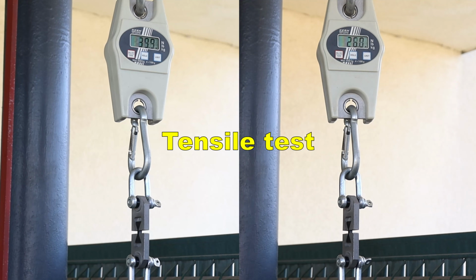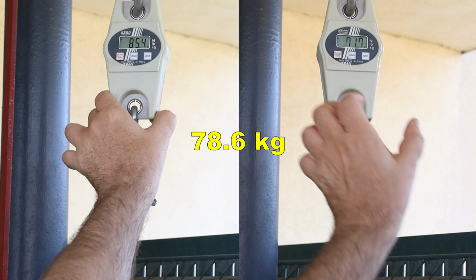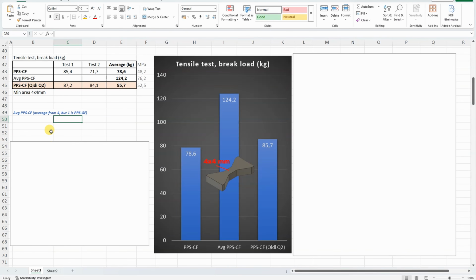Tensile test, horizontal printed objects. Well, for comparison, I will use the average PPS-CF, but I have only 4 in that summary table for my patron supporters, and actually one of them is glass fiber reinforced, but this is what I have, so let's see the numbers. Actually, this number is not bad for the average filament type, but compared to the average PPS-CF, this is very weak. And actually, I checked the datasheet, I was expecting something similar, so that's why I reprinted everything on the Qidi Q2, using almost the same parameters, and I got a very similar number.